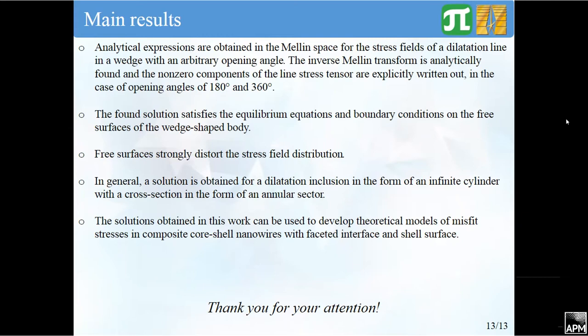The found solution satisfies the equilibrium equation and boundary conditions on the free surfaces of a wedge-shaped body. Free surfaces strongly distort the stress field distribution. The solution obtained in this work can be used to develop theoretical models of misfit stresses in composite core-shell nanowires with faceted interface and shell surface.